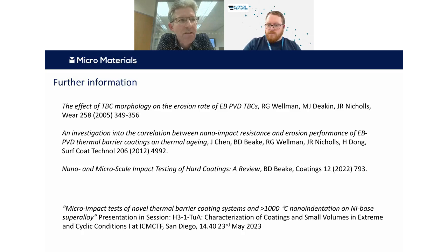I didn't talk about it much, but actually one of the things that we presented was more microscale rather than nanoscale impact wear, because then we could switch towards these 25 micron probes. And they're made of diamond, and the geometry of these things is remarkably durable. They can handle many thousand impacts without changing their geometry, or potentially even hundreds of thousands of impacts. Whereas if you had a very, very sharp cube corner impact probe, I think then you might have to be a little bit more cautious.